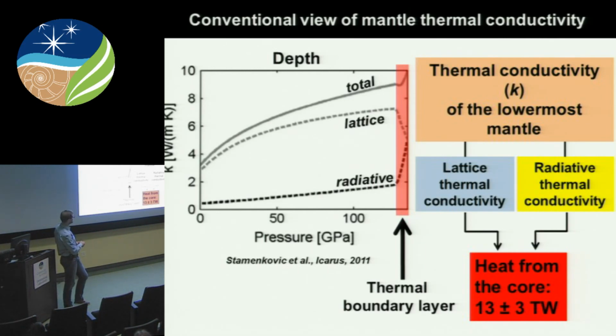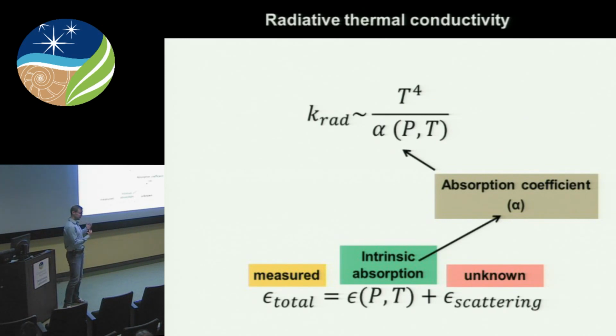However, there is a conventional view on what thermal conductivity is in the deep Earth. And here you can see the total thermal conductivity as a function of depth compared to the lattice and radiative components of total thermal conductivity. So an interesting thing happens in the thermal boundary layer, and this is the region that we're most interested in. Here you can see that radiative conductivity shoots up and lattice conductivity sort of goes down. So these opposite changes basically cancel each other out, and you end up having a total thermal conductivity that remains approximately unchanged. So what I want to say is that this total thermal conductivity is a very important quantity because it allows constraints on the heat transfer out of the core, the rate of heat extraction out of the core. And that energy value is very important for constraining geodynamic processes in the lower mantle because it provides energy for them.